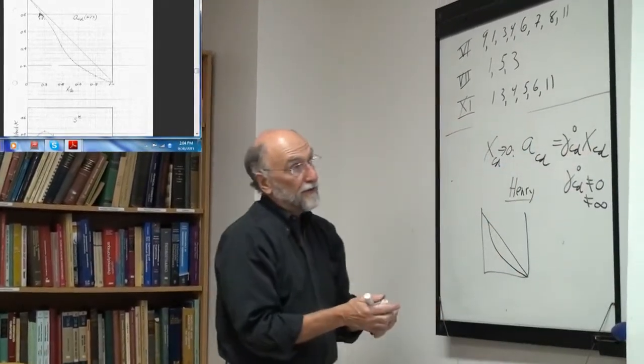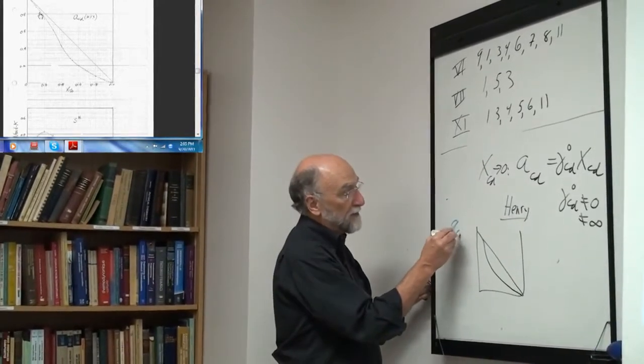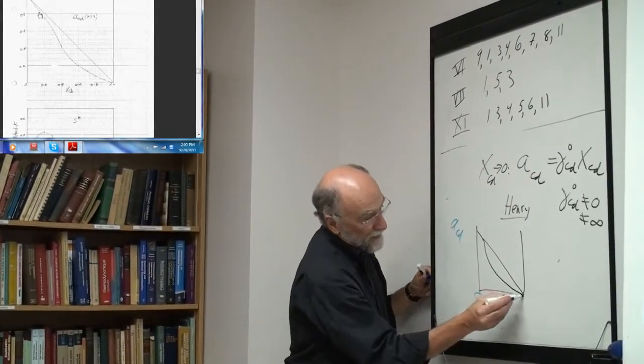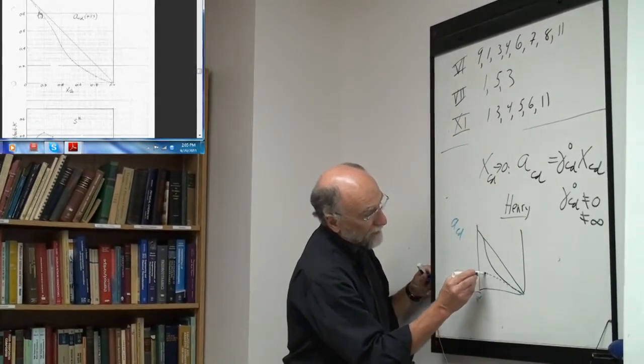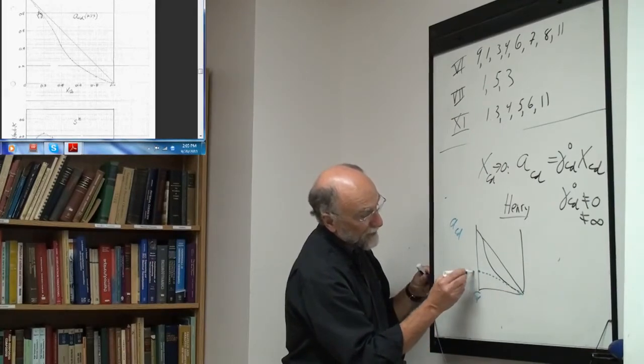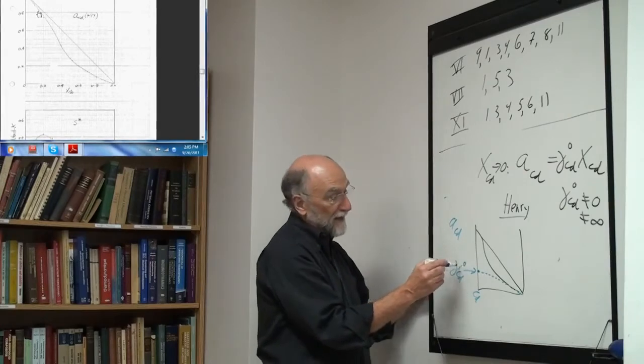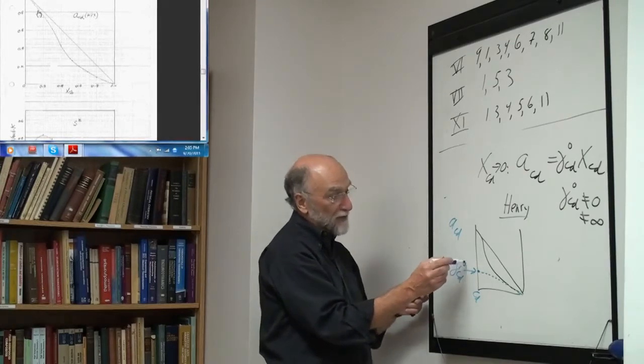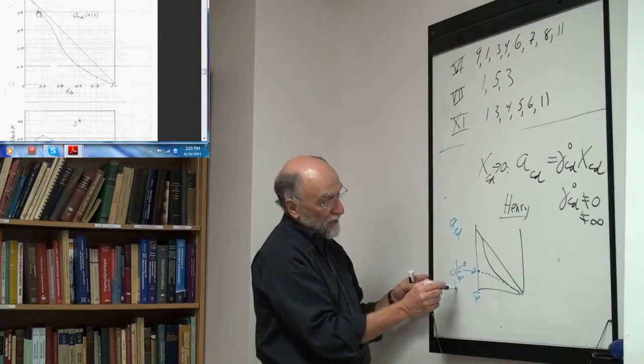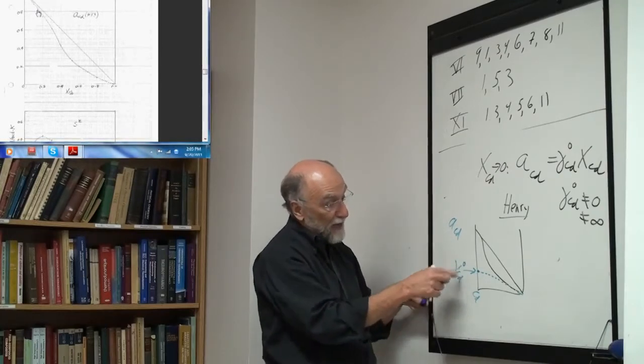So this graph here is the activity of cadmium, and this is pure cadmium here. I take the limiting slope here, take the slope at 0, and step it up here. And this is called gamma Henry. Gamma naught doesn't mean ideal state, it doesn't mean standard state, it means limiting case. This is called the Henry activity coefficient, or gamma Henry.